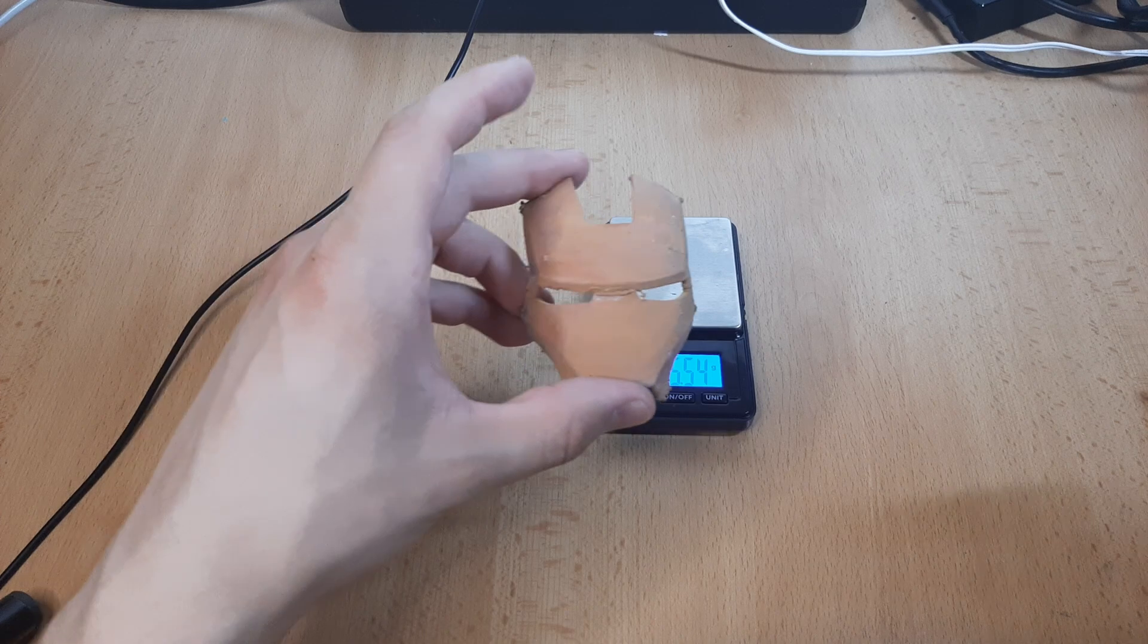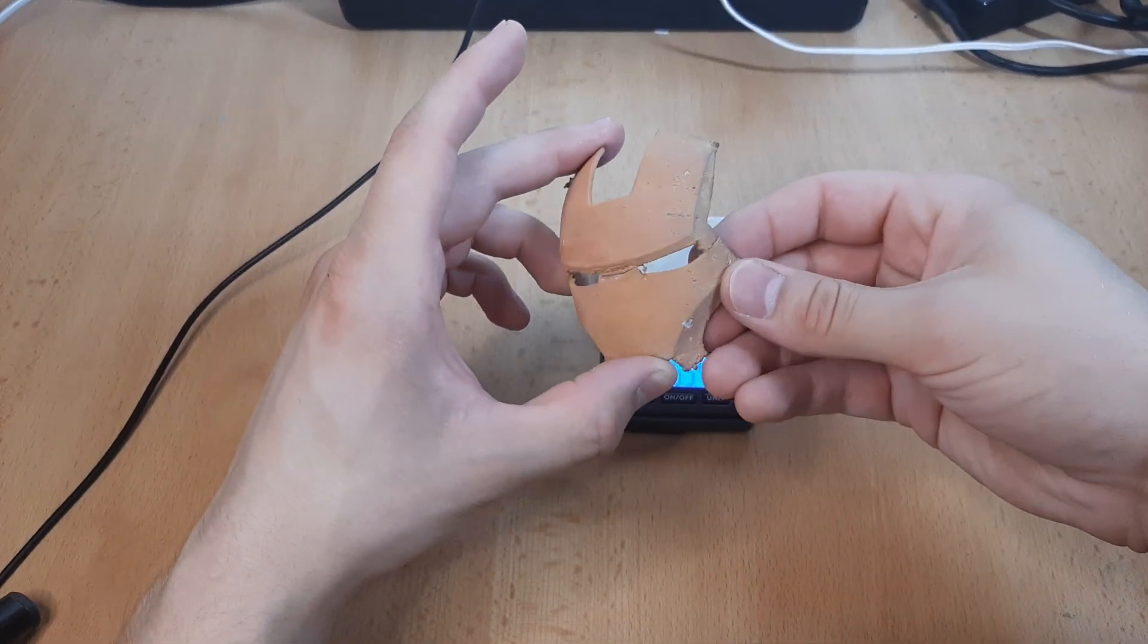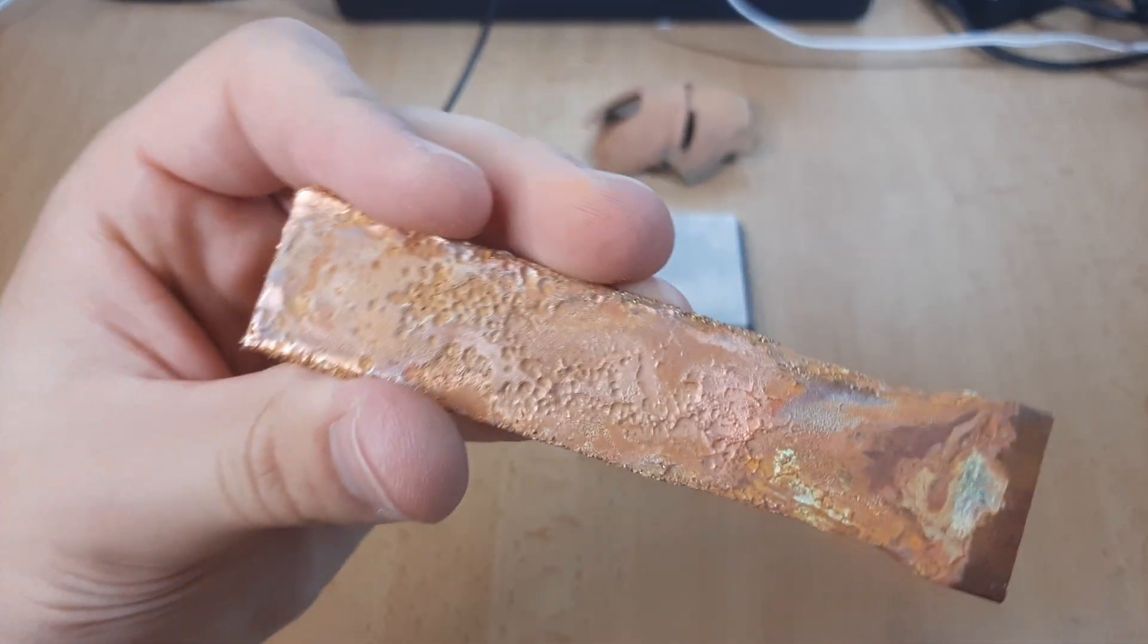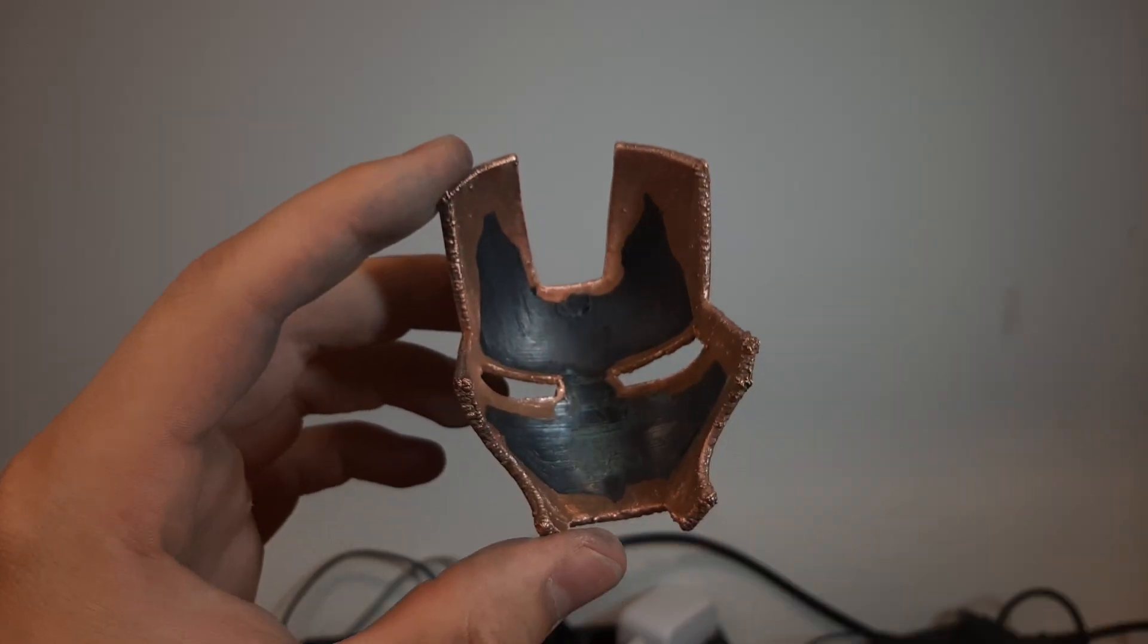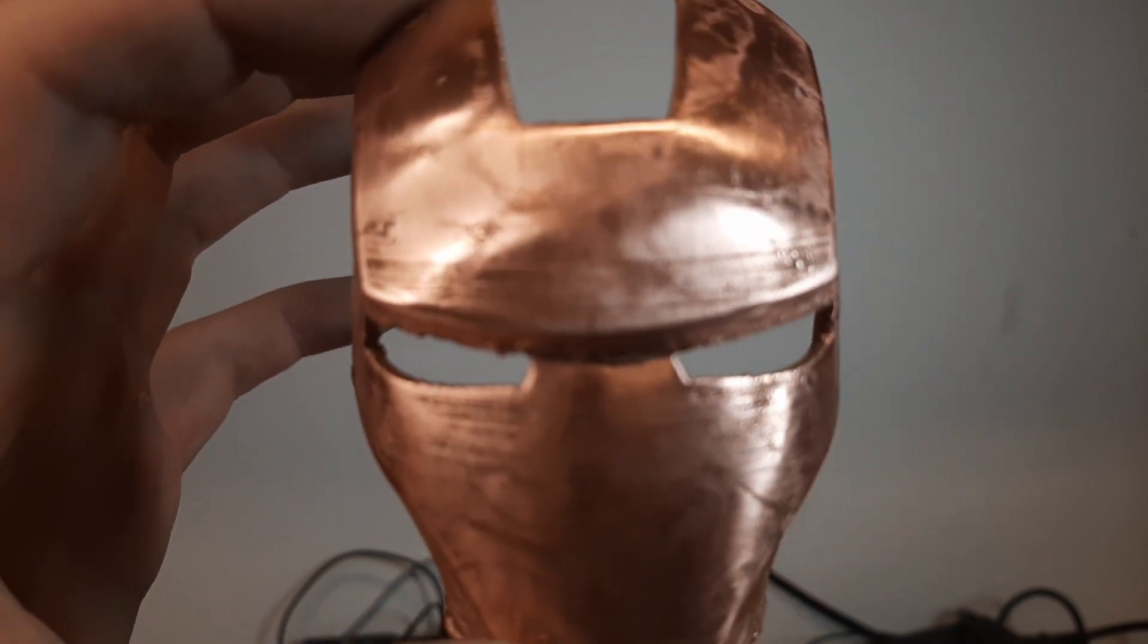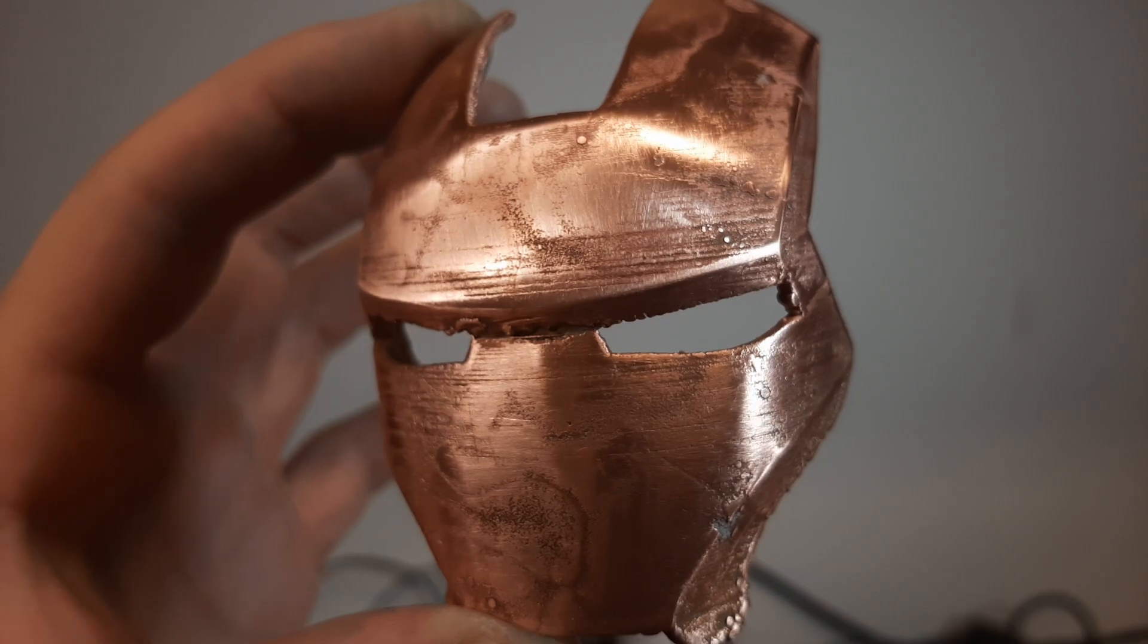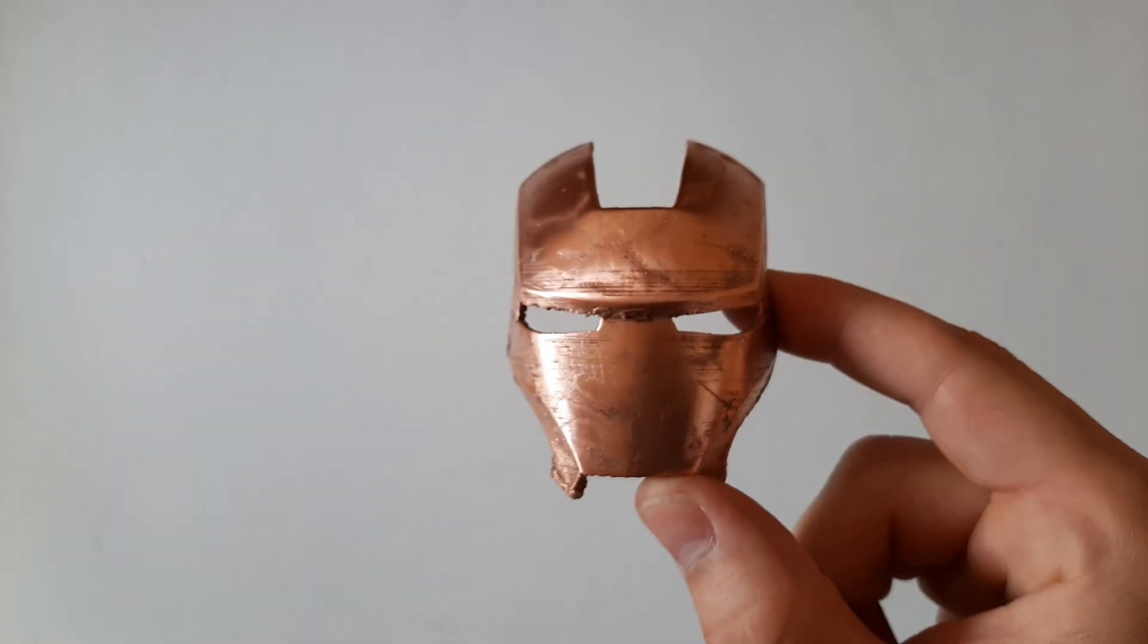I let the helmet plate for 30 hours. The copper layer is much thicker and weighs about 30 grams. You can see how corroded the electrode is. This is looking much better, although the back still didn't plate. I think this is because the motor spins too fast. Otherwise, it has almost mirror finish. It feels like a solid piece of metal too. It has some weight to it.